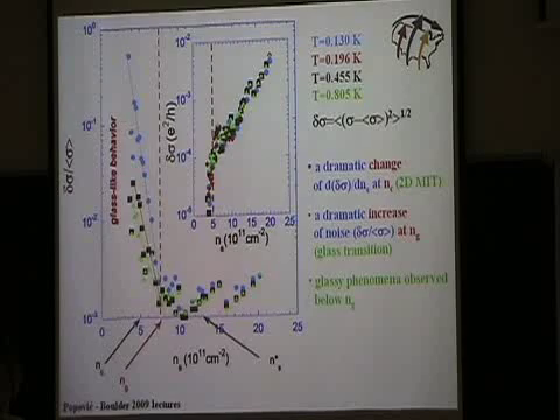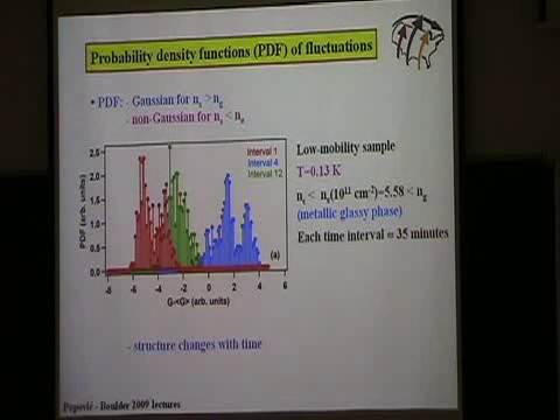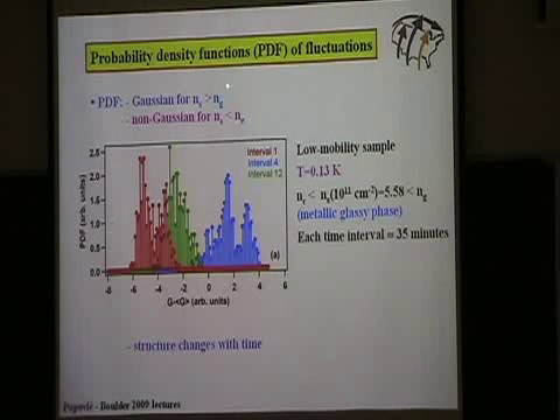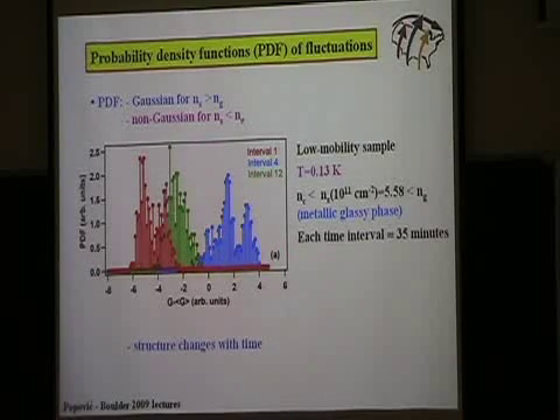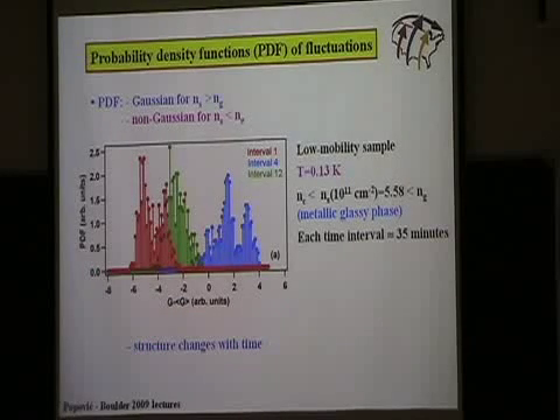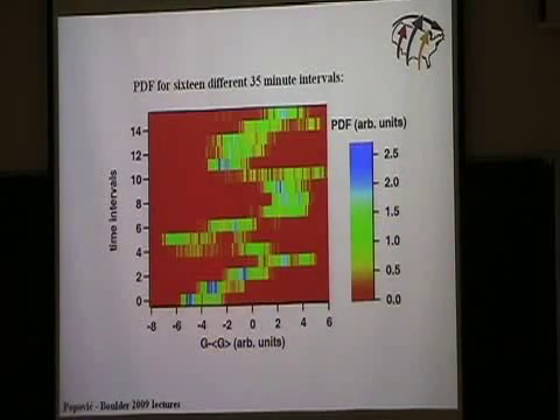So, for all those of you who like to look at PDFs, this is what we get. For densities above Ng, we get nice Gaussians, and I'm not sure why I did not include that here, probably because I thought it was not interesting. But for all densities below Ng, we get some complicated structures that depend on when you do your measurements. So for example, over the first interval, each one was about 35 minutes, you get something like this, then you do your measurement later, you get something like that. So the structure changes with time, and you can see how it changes here. So these are 35-minute intervals.